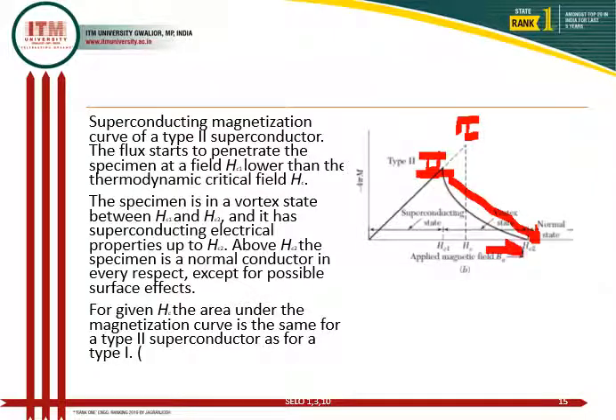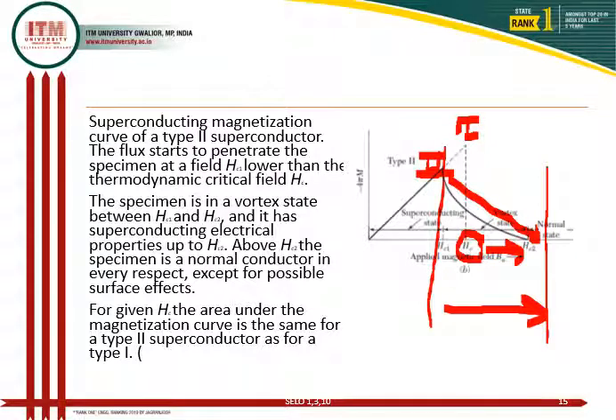and this Hc is higher than the Hc that we have chosen. It's called critical magnetic field. So from first region to this region, this is a very long region which is called vortex state, where the superconducting material lives in two forms: mixed state, and it has superconducting electrical properties. Above Hc2 it will again behave as a normal conductor. However, for a given Hc, the area under the magnetization curve is same for type 2 as type 1. You can see from here, if you add this area and this area will be same.